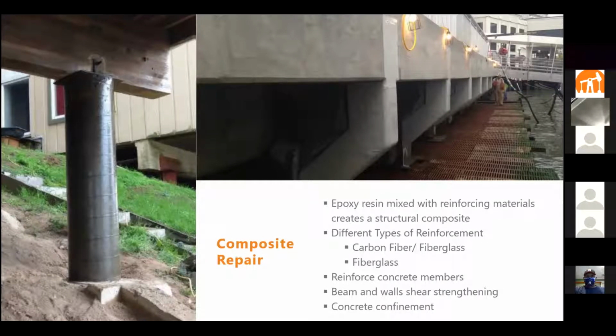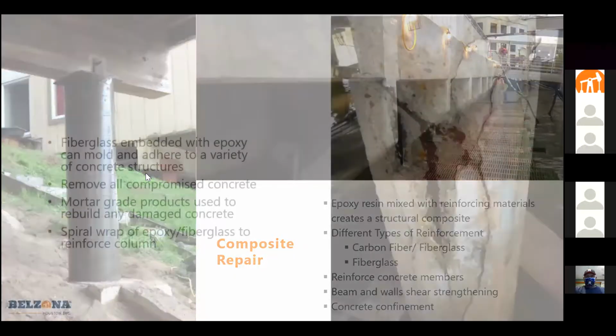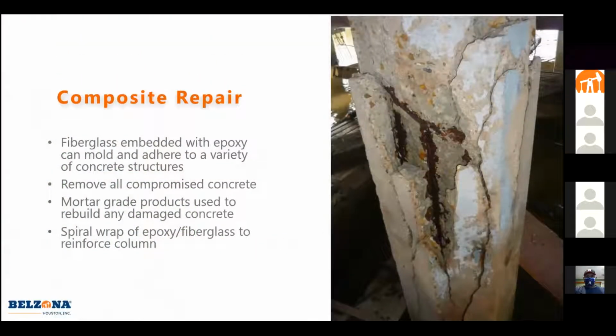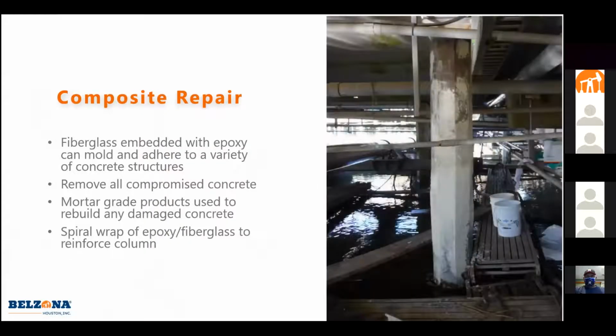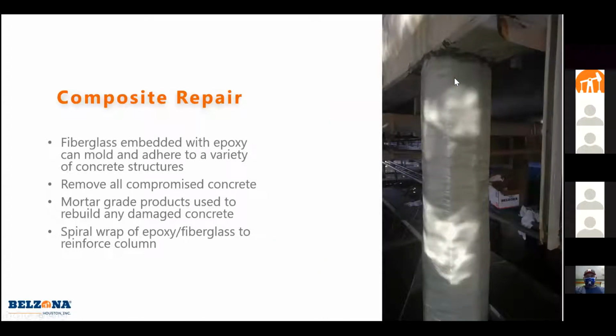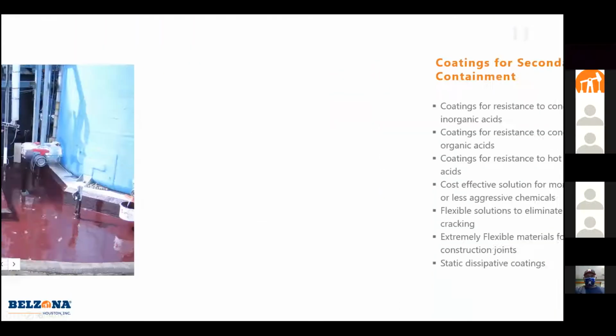So if your concrete is being compressed and it's actually cracked due to compression, we can wrap it, and that's what this picture on the left is. We can wrap it with a composite to confine it and give it some more compressive strength. And this is an example of a concrete that was just corroded. Again, not a secondary containment per se, but just showing you the capabilities. This is offshore. We used our rebuild product to rebuild concrete back to its original profile, and then wrapped it all to give it a little bit more compressive and shear strength with a fiberglass wrap.